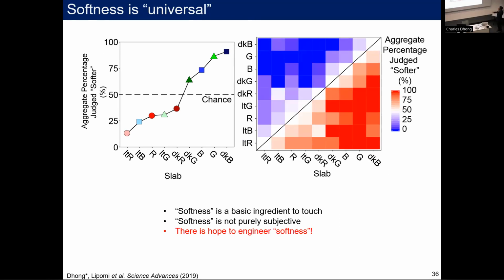So beyond that, I think the most important finding we had at all was this: this is the aggregate data, but on the right, this is the raw data. So this is when someone tested dark blue, and did you think it was softer than red? Then I would have recorded the result here. And so this is all my head-to-head data of every single sample versus each other. This is reflected around this line, which you don't have to look at, but just up here is all my raw data from all my samples. And the most important part of this plot is that there's no red above this line, and there's no blue below this line. And that's not some feature of the way this is plotted. That's something about my data.